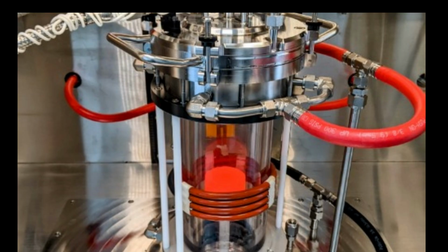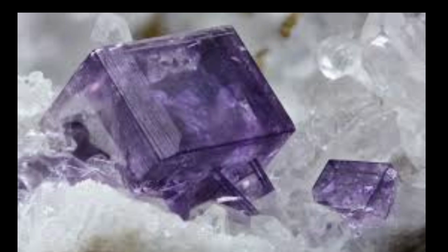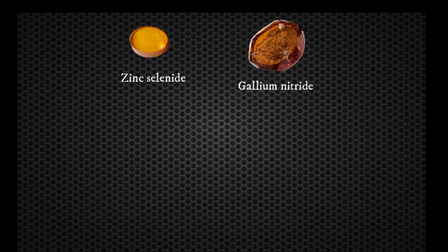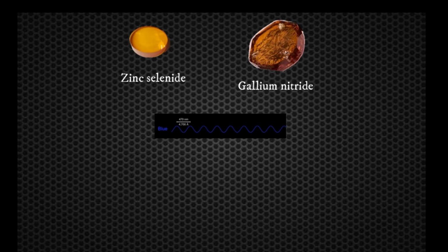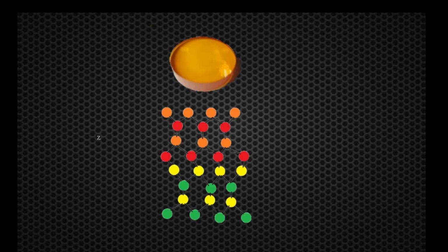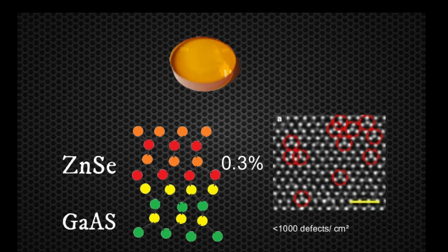But now the question was, with MOCVD under his belt, which material should he research? By this time, scientists had narrowed the options down to 2 main candidates: zinc selenide and gallium nitride. These were both semiconductors with band gaps, theoretically, in the blue light range. Zinc selenide was the far more promising option. When grown in an MOCVD reactor, it had only a 0.3% lattice mismatch with its substrate, gallium arsenide. Therefore, zinc selenide crystal had about 1,000 defects per square centimeter, within the upper limit for LED functioning.